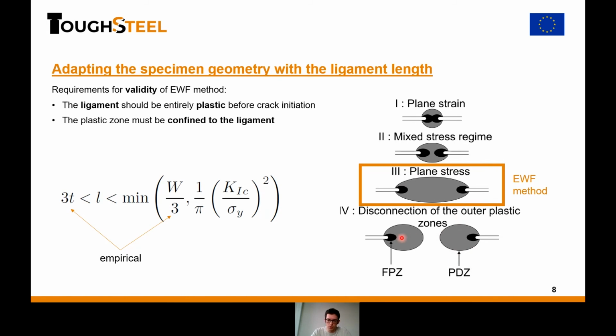process zones will not interact between each other, and so you don't have this relationship where all your samples will be geometrically similar, and so you cannot have your total work divided in the two contributions. And in the other way, if the ligament length is too small, you start to have your fracture process zone interact between each other, and the stress state will not be similar between each sample again, and so the method is not valid either.